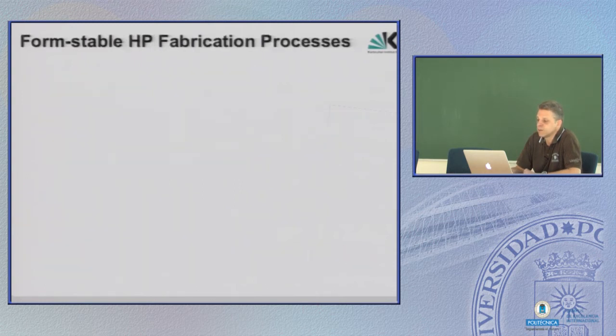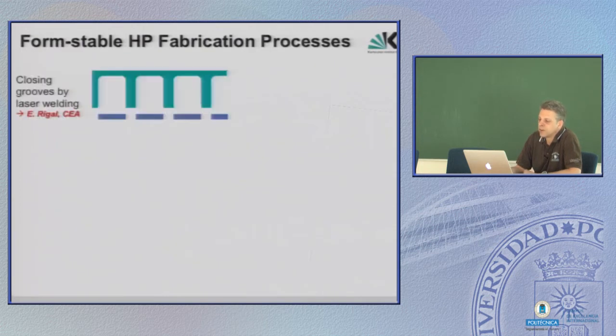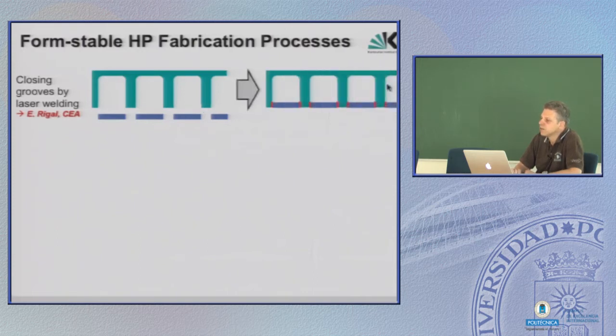This is what I have just mentioned, such form-stable fabrication processes. There was one idea from CEA that you use a blade, mill these grooves of cooling channels in it, and then you weld 3 meter long thin plates on top to close the cooling channels. Then you would end up in such a configuration, and now the cooling channels are tight here.